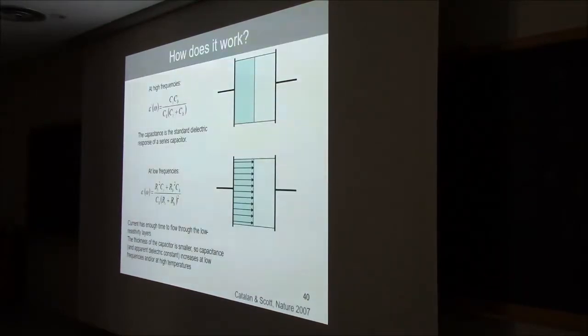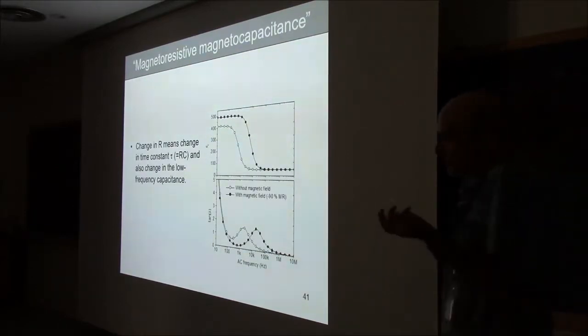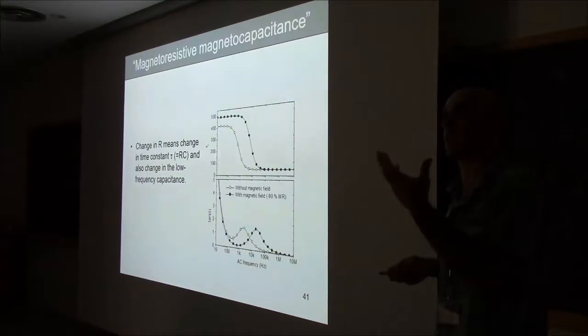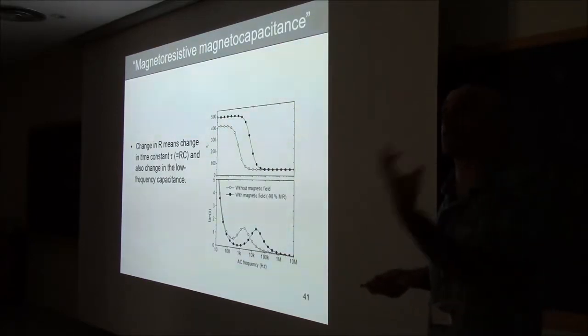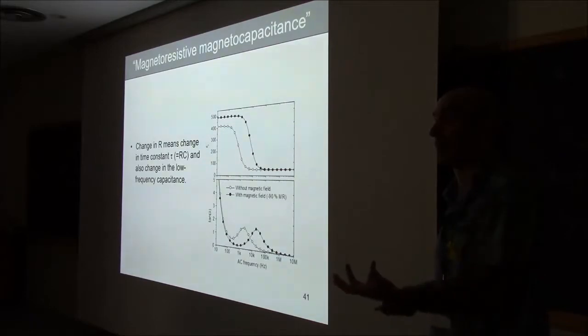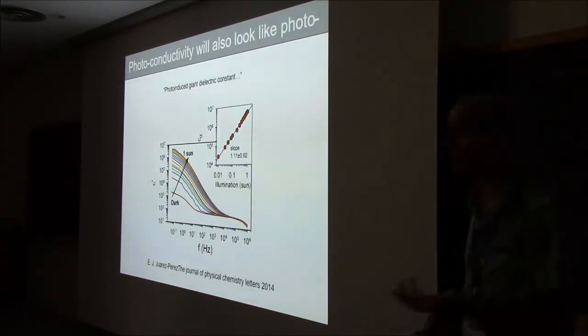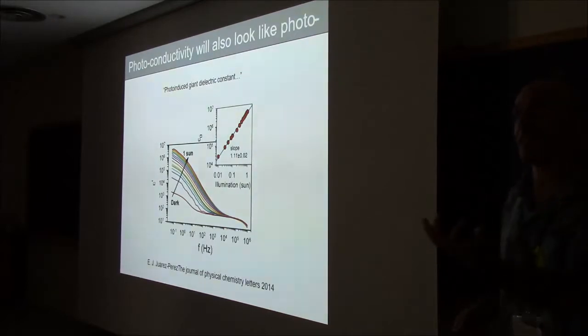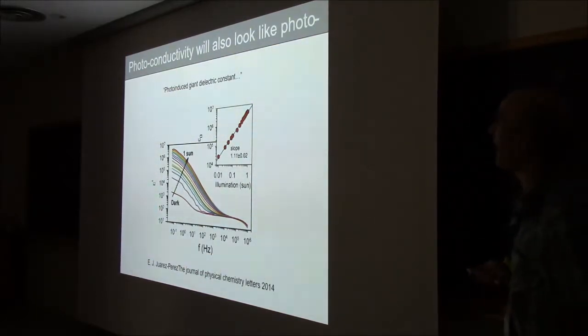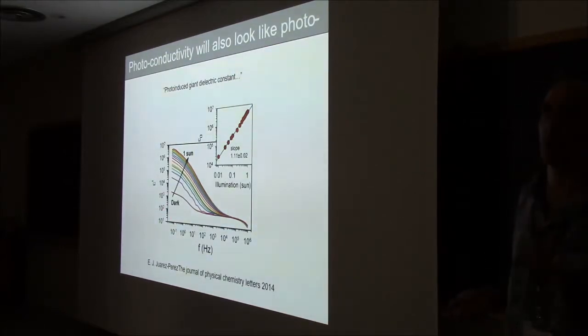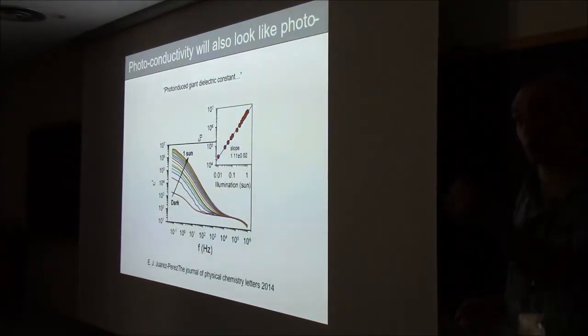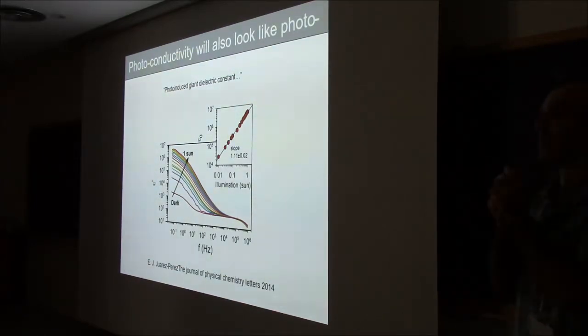And of course, you can modify the capacitance if, of those two resistive leaky elements, the resistance of one of them depends on a magnetic field. So if, say, you have a magnetoresistive material, you will measure a magnetocapacitance, but it will not be a magnetoelectric effect. Okay? It has nothing to do with magnetoelectric coupling. And if your material is photovoltaic, the same thing will happen. So if you shine light on your material that is leaky, the light will make it even leakier, and so your capacitance will go up, and so your apparent dielectric constant will go up, but this is not a real dielectric constant. Okay? So if you're going to measure the dielectric properties of photovoltaic materials and the response to light of those dielectric properties, be aware that you're not measuring a dielectric response, or not only a dielectric response.